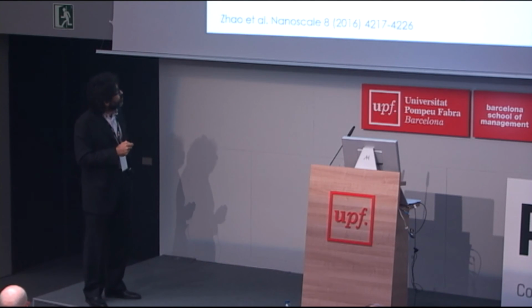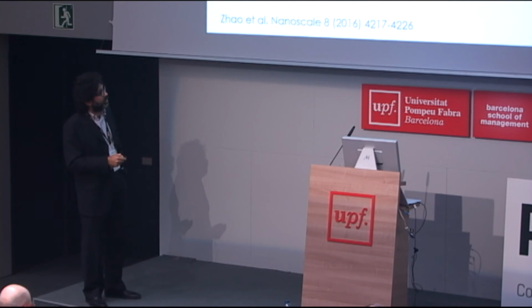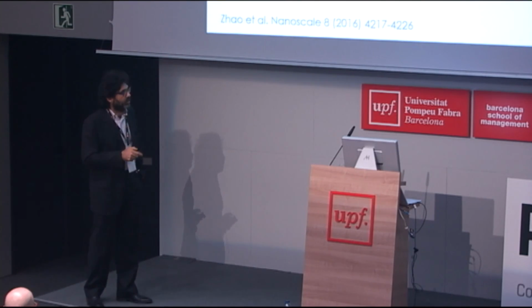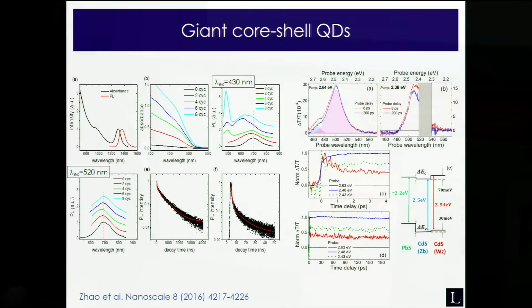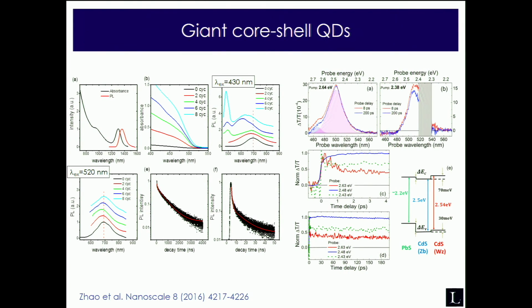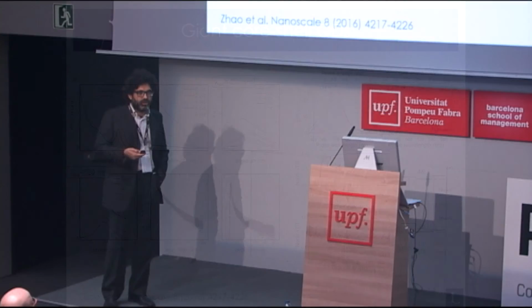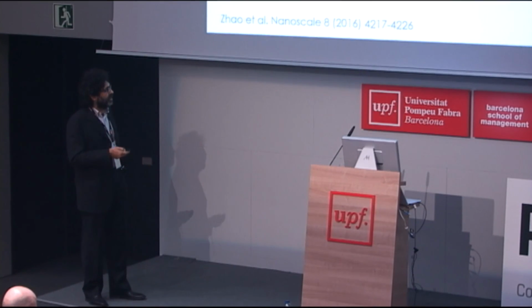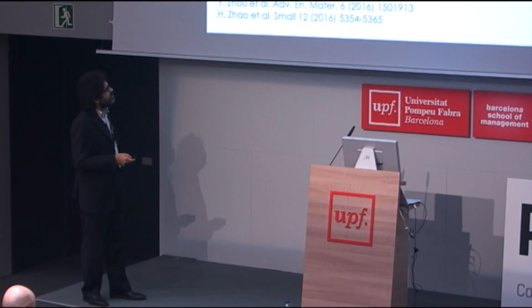For the proper thickness of the shell, we got a visible emission and an infrared emission. The main explanation for this, through time-resolved ultrafast techniques—I'm not an expert on that—is that while you have quite high delocalization of electrons throughout the structure, the holes are pretty confined either in the core or in the shell, and they cannot communicate with each other.